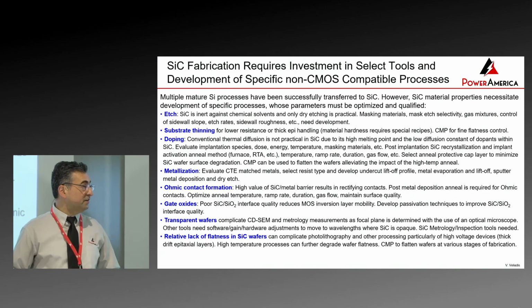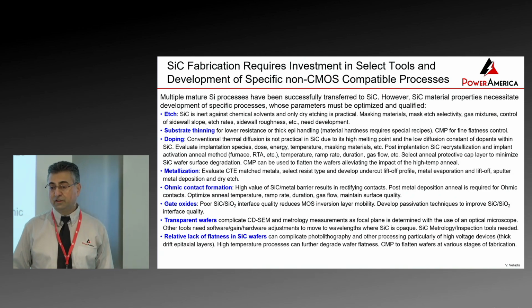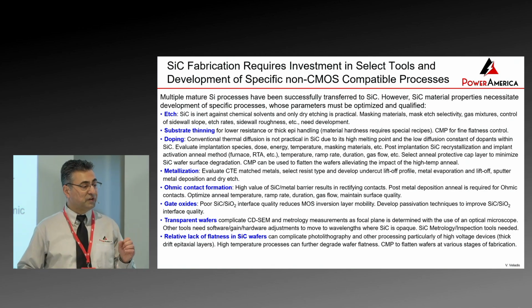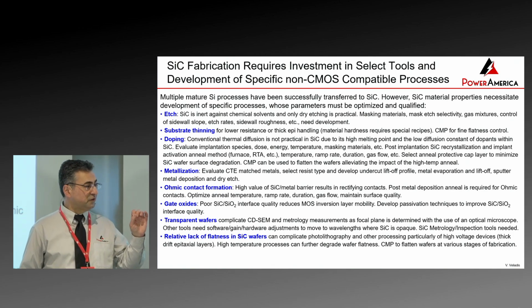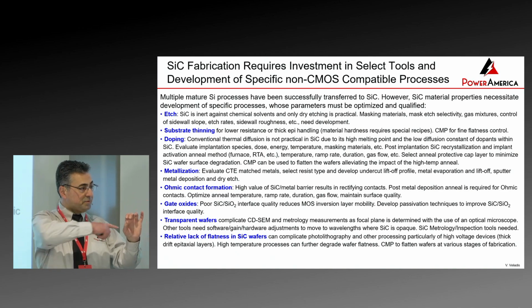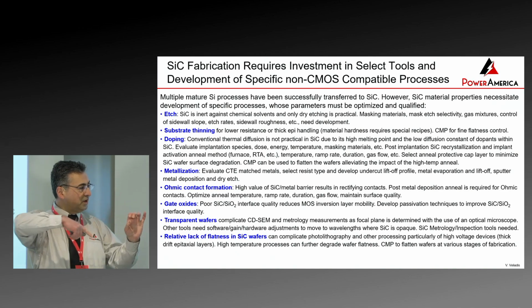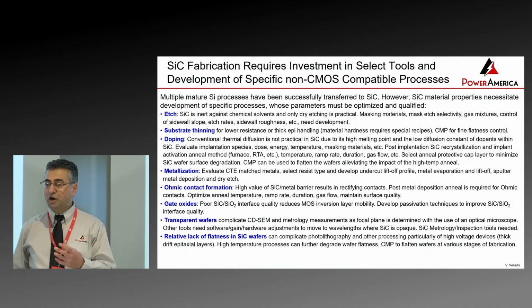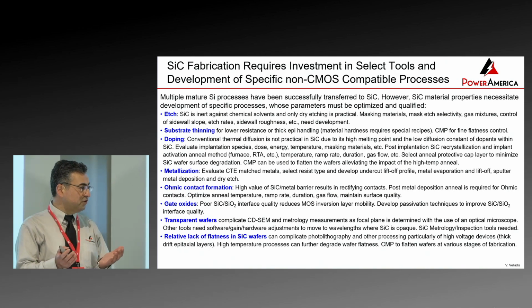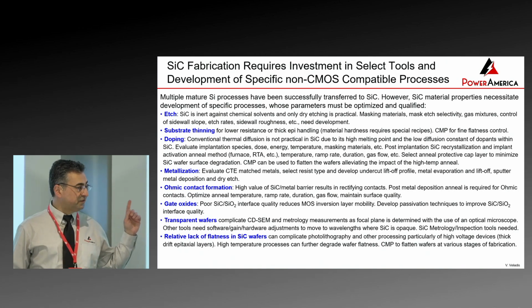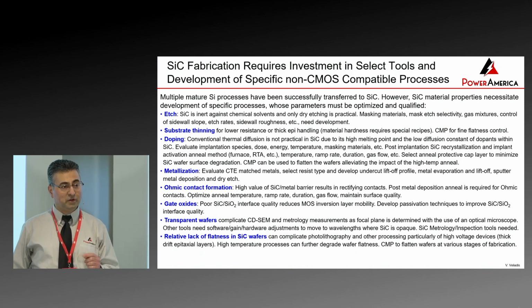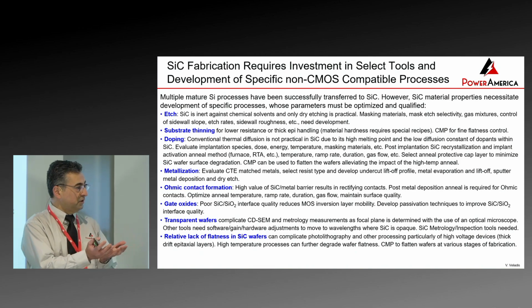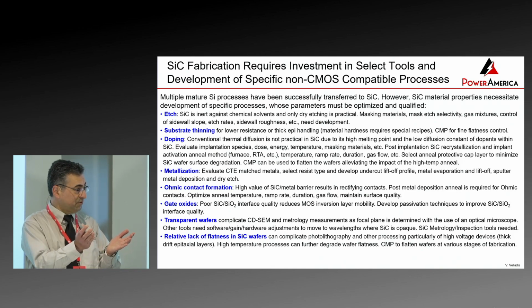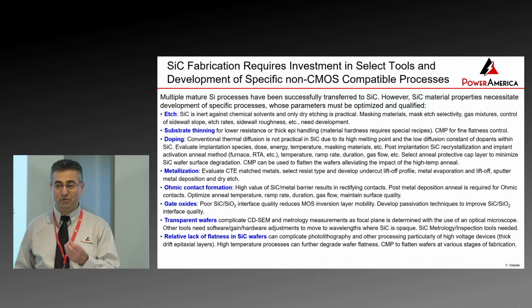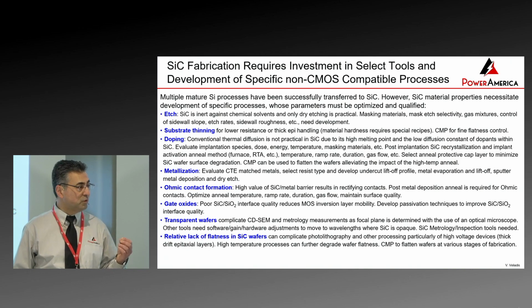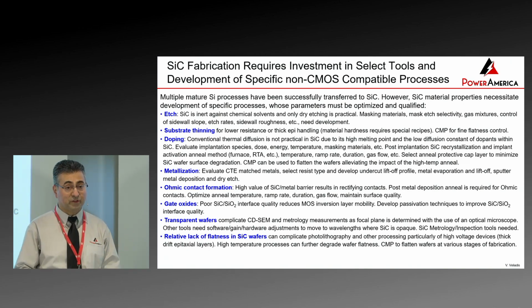The relative lack of flatness, that's a really big one. Silicon is flat. I was seeing a presentation saying that the flatness of silicon is like a tennis ball, while the area of Japan, Korea, and Taiwan, that big area, is silicon carbide. The planarity is not very good, and when you get to that implant, 1600-degree implant activation, you can sometimes see a wafer turn into a potato chip, okay? And that's not good, because you will not be able to focus with a stepper. So planar wafers are a very big thing, of course, lowering the defects as well.